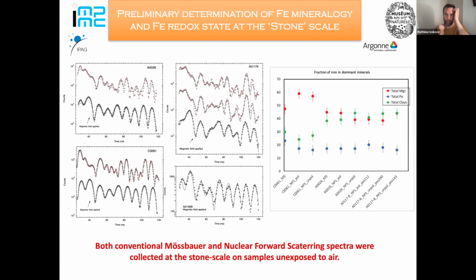Then we collected NFS spectra, a lot of them. So you have a few of them shown here with different grains. Samples were collected in focused and unfocused beam with polarized and unpolarized configuration. And we fit the data.